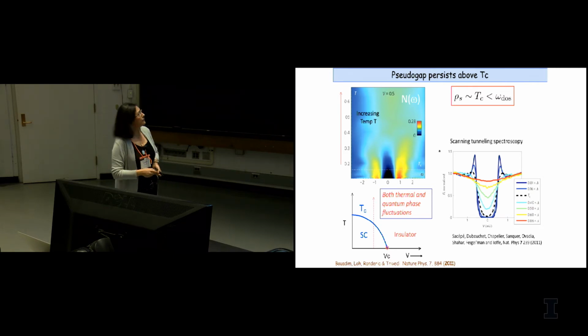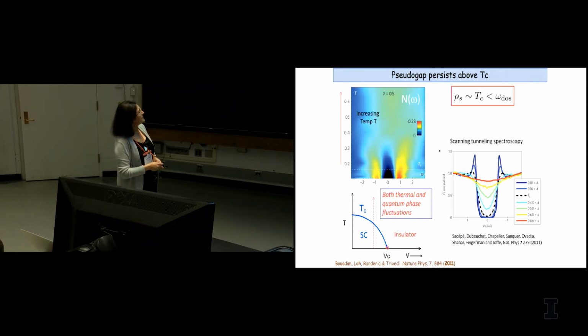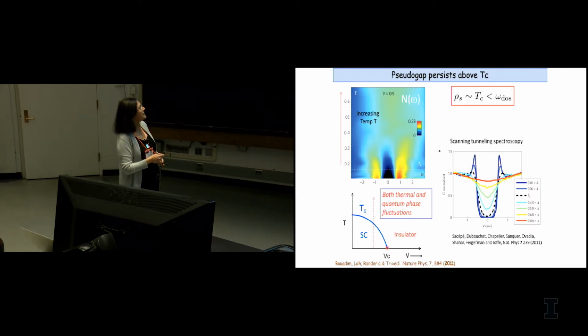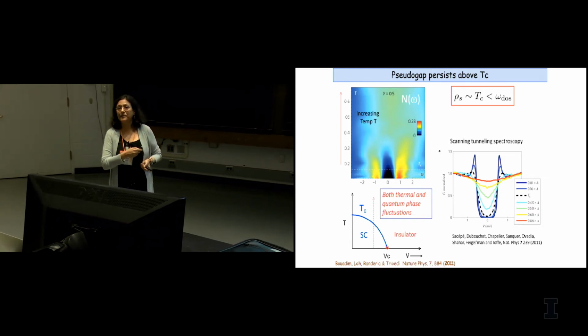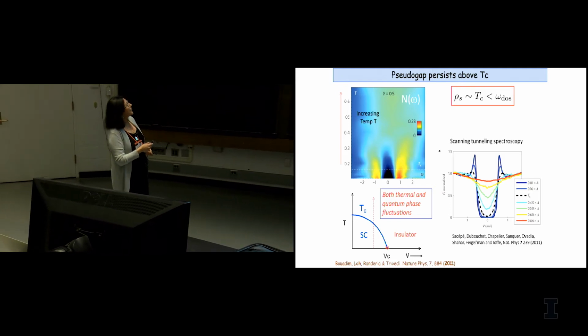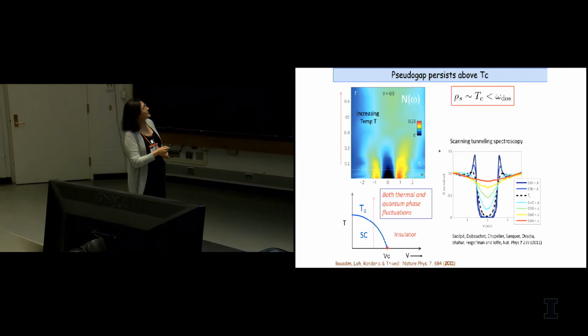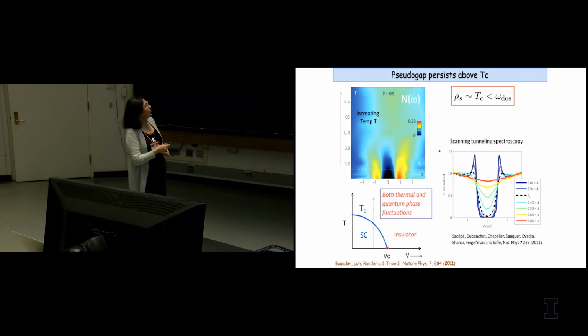If you take a particular disordered system and go up in temperature, then one could see that you get this pseudo gap where at Tc, the superfluid density went to zero, but the gap closed only at a much higher temperature that you can call T star. That's shown here in the single particle density of states. This is not experimental data, it's actually theory, showing the single particle density of states with a hard gap at low temperatures. The white dotted line is Tc, where the superfluid density vanishes, and you can see this gap still persisting.